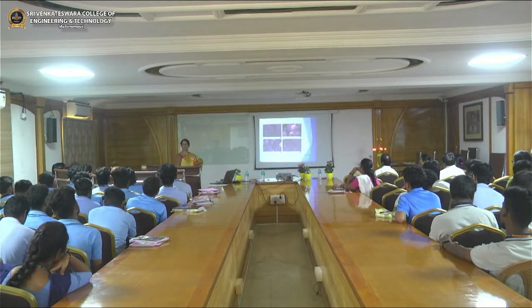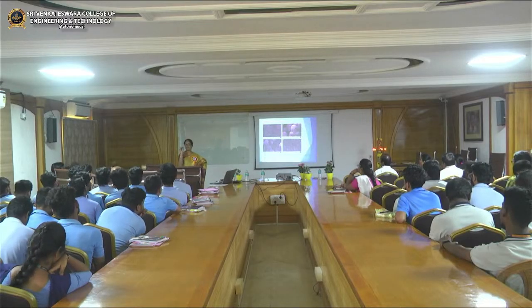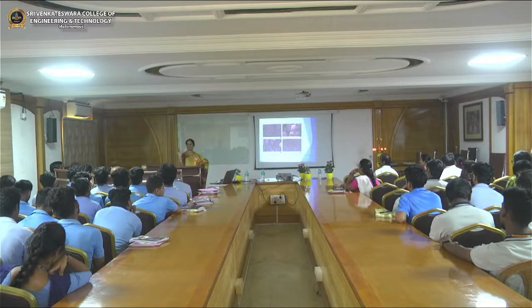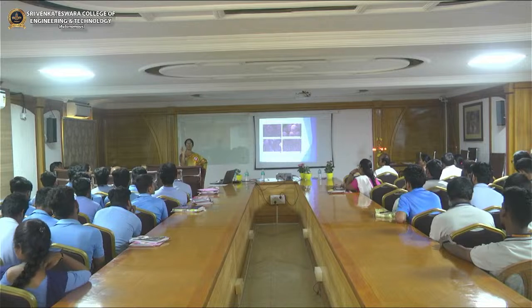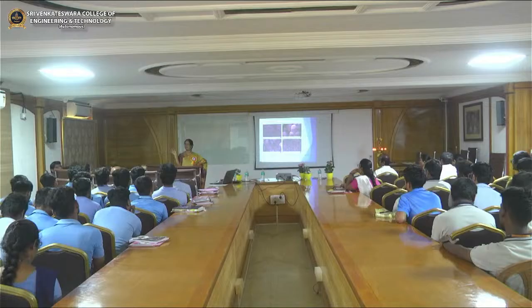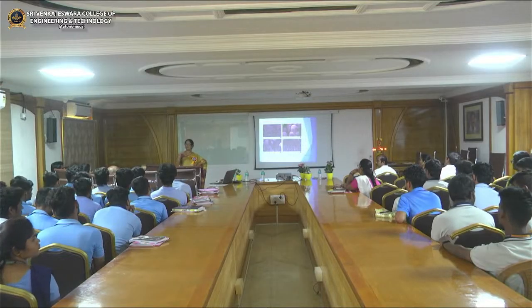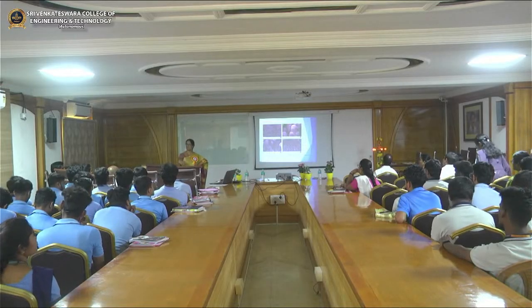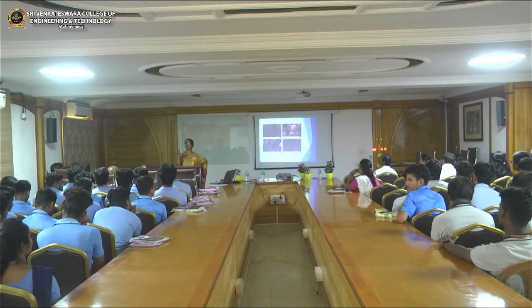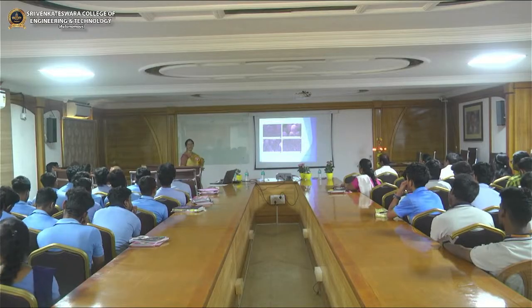When you take the chemical co-precipitation method, we will get only particles. Particles have dimensions of 30 nanometers, 50 nanometers, 60 nanometers like that. We will get only nanoparticles by using the chemical process. It is not possible to get a variety of nanostructures by using the chemical process. With the hydrothermal method, we can get a variety of nanostructures: wires, rods, belts, flowers like that.